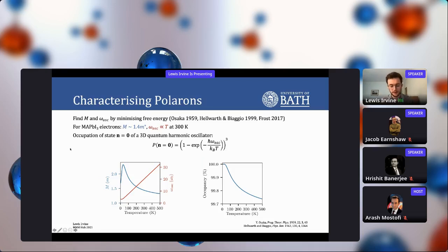Now this work was done by Frost in 2017, which we picked up and used again as our starting point. So you take the free energy that was derived by Osaka in 1959, and you minimize it to find the two parameters that you need to fully characterize your polarons. That's the mass and the oscillator frequency. So for electrons in MAPI, we see that at room temperature you get about a 40% increase in mass over what you would get in your regular band electron. And we also find that the harmonic oscillator frequency is proportional to the temperature. We also worked out the occupation of the ground state of the 3D quantum harmonic oscillator. And we see that for all temperatures that we're interested in, the occupancy is basically 100%. So we're going to carry on assuming that our polarons are always going to be in the ground state.